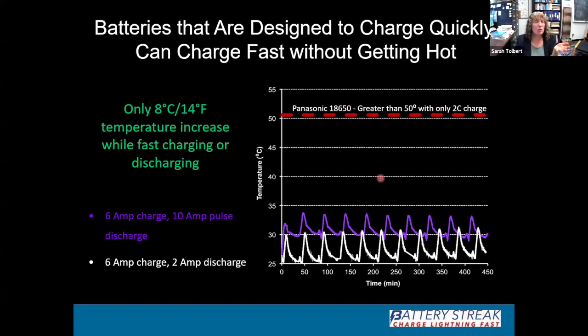If instead you take one of these porous holey batteries and, in white, we charge it fast and discharge it slowly, it goes from room temperature to a calm little 30 degrees. That's barely warm to the touch. If you charge it fast and discharge it fast, it heats up a little more, but it is still way below body temperature. It's only up to about 33 degrees.